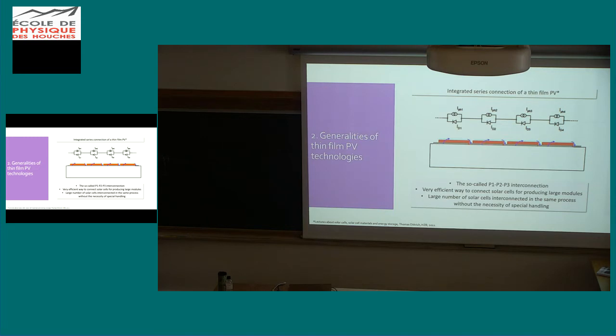This ensures that the series resistance of your layer is not really relevant during the operation of your solar module, and also permits choosing the width of your cell and the number of cells you connect, to have the power that you need for different applications. So it's useful in both ways. And this is one of the main advantages.